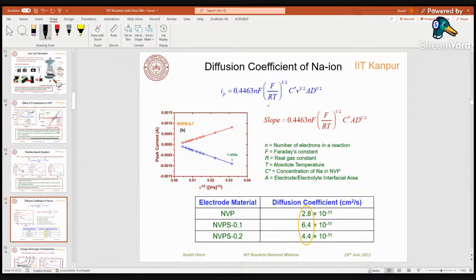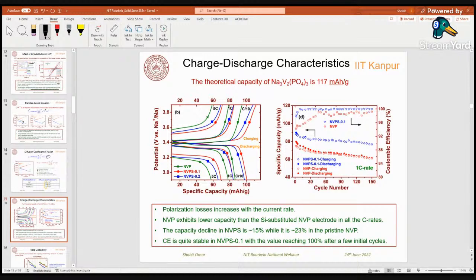We have also tried to calculate the diffusion coefficient of sodium ion using the Randles-Sevcik equation, and we observed that NVPS 0.1 shows higher diffusivity compared to your NVP cathode material. Now look at the electrochemical performance of these half cells. At different current rates, which are C/10, 1C and 5C, you can see that the polarization losses increase as you increase the current rate. And the NVPS cathode shows higher capacity compared to your NVP cathode, and this happened at most of the current rates that we have tested.